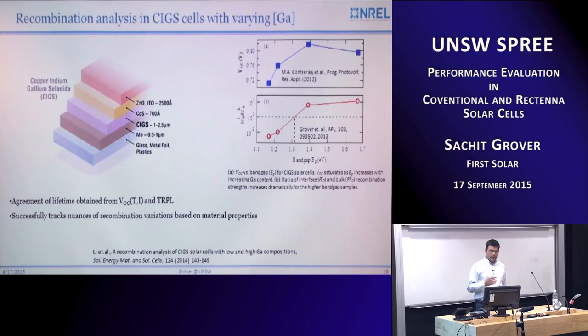We did a similar thing for the CIGS cell. And the problem there was a little different. As shown in this diagram here, we were varying the band gap of this CIGS by changing the gallium concentration. And we did not see a proportional increase in VOC. This is published by the CIGS group at NREL in 2012. And they were suspecting Fermi pinning as a cause for this rollover in VOC with band gap.